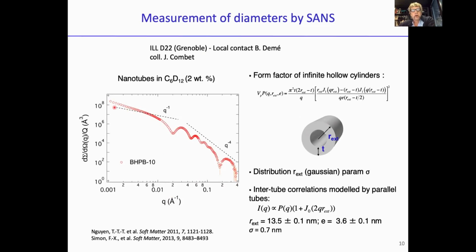And this curve comprises two parts. The first part is a straight line where the variation is close to q to the -1. And this is very characteristic of very long and rigid objects. So this is the form factor of a rigid rod. And then the second part of the curve comprises many oscillations. And these oscillations describe the cross section of these objects.